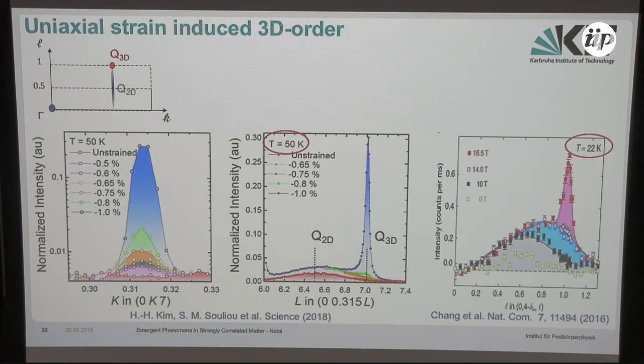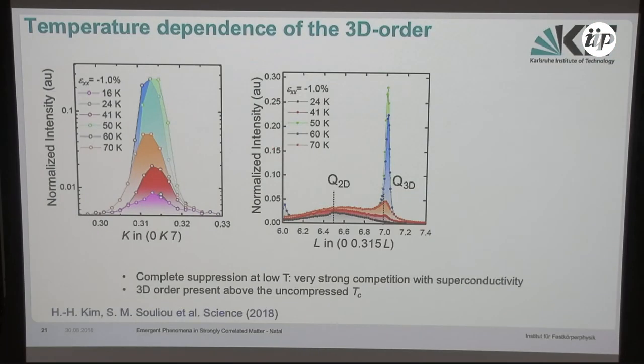So we investigated the temperature dependence a bit more. We could not go to very high temperature, unfortunately. But basically at 70K, which means above the nominal critical temperature of the sample, we can already induce the 3D order. It means we can really go from the 2D to the 3D order just using uniaxial pressure. And what we see is that the peak is maximized at 50K and then decreases and ends up completely disappearing in the superconducting state.